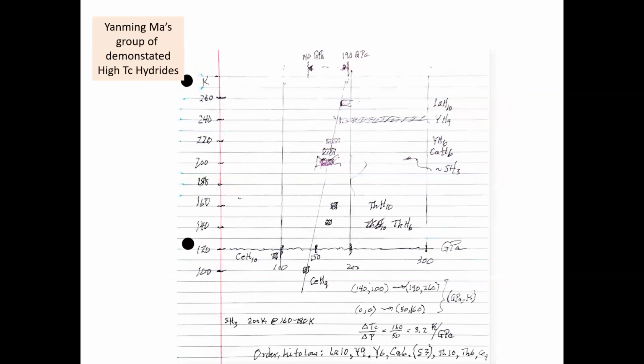Okay, again, I got out my software and I just plotted, there's no temperature here. There is temperature TC scale here and pressure scale here. You can see 100 gigapascal, 200 gigapascal, and those 8 follow right along here, except for this one, cerium, is out of place. And it looks like to get to a higher TC material up here, you just need to apply more pressure. It's not that simple. Well, the next thing that was discovered, which I will show you in the next few graphs, was not along this line. And this is just a small set of data. So I showed this partly to be sort of humorous and not to be something to take too seriously.